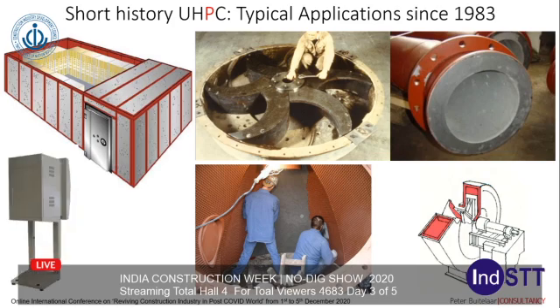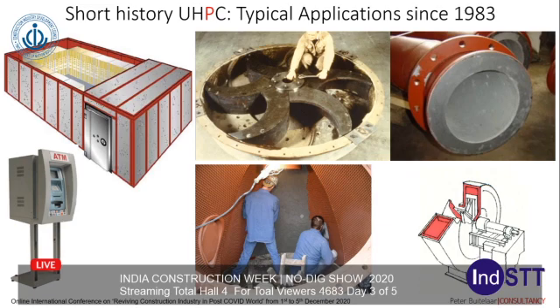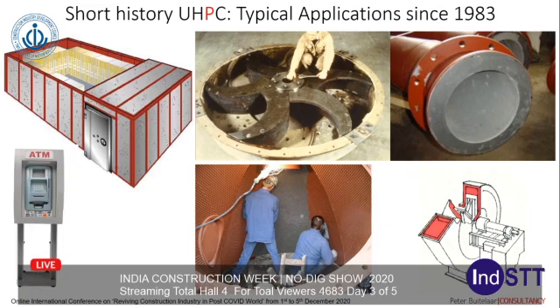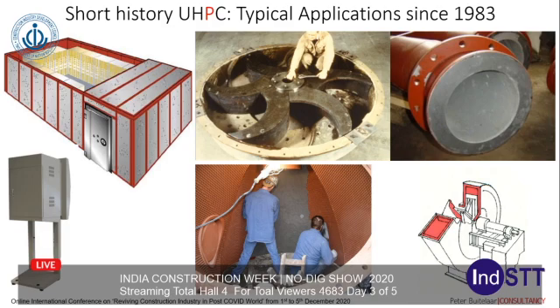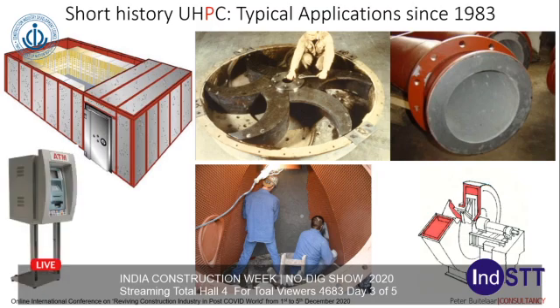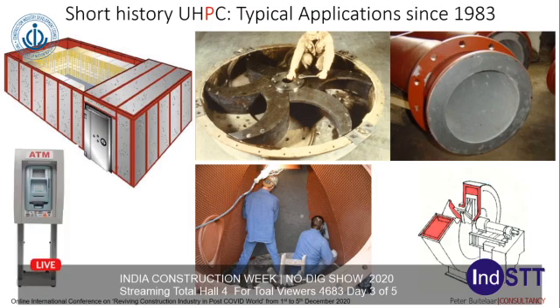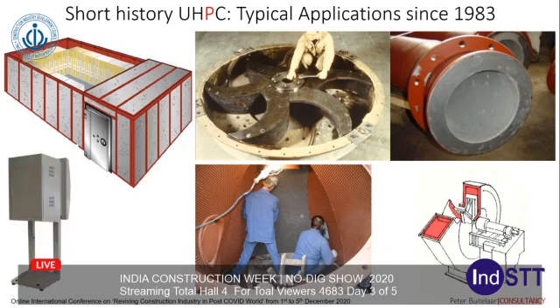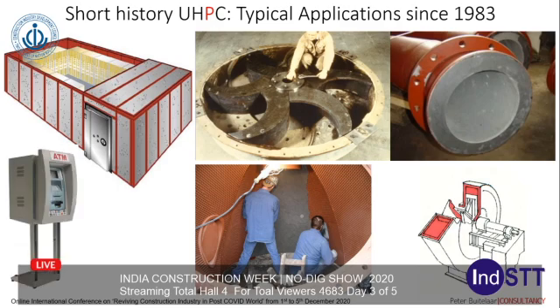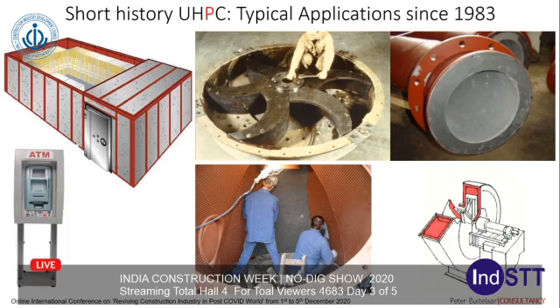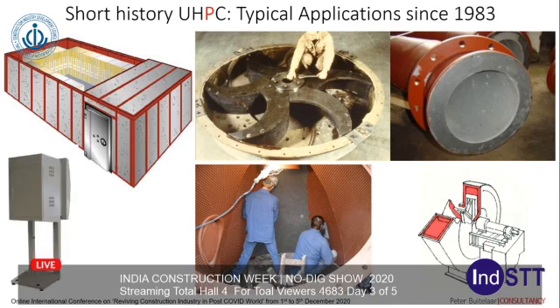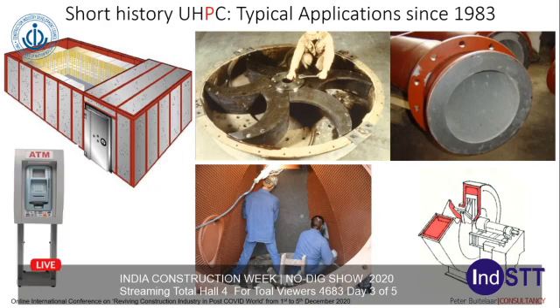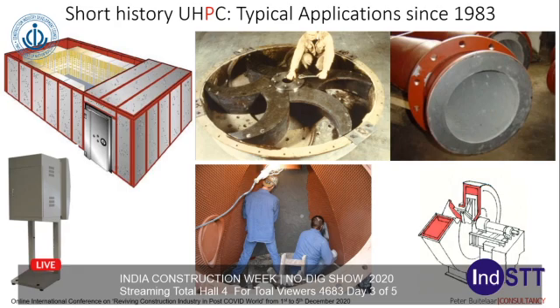Security industry. UHPC is used as a barrier material in vaults, strong rooms, ATMs and protective structures against explosives and other threats. Wear protection. UHPC is used as wear lining in systems with abrasive wear, like in cement factories, coal-fired power plants, steel factories, etc. Very hard, wear-resistant aggregates like silicon carbide, corundum and calcined bauxite are used while the material can be applied by casting, spraying, hand troweling and prefab elements. The UHPC can replace many other materials and is used, for example, to replace the cast iron scoop feeder in cement factories, resulting in a much longer service life.